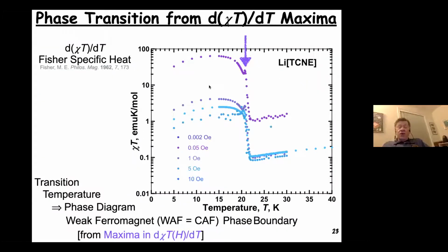We can also see some of that data mimicked by looking at the change in chi T versus T, d(chi T)/dT. And this is Fisher specific heat. And Fisher has convinced people that in fact, this mimics specific heat data, not chi versus T, but chi T versus T. And looking at the derivative, which I'm not showing, I'm just showing the maximum, which is in fact the derivative of it. We're just not showing it. And we can get a transition that's at the weak antiferromagnet, weak ferromagnet phase boundary to do that.